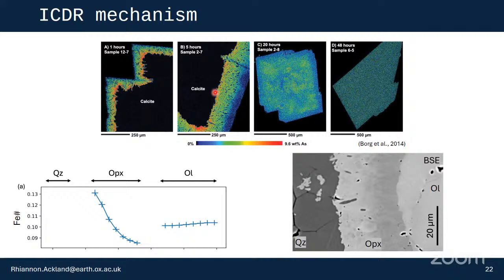nanoporosity of the rims. And as these experiments ran to completion, they did eventually equilibrate and become homogeneous apatite in equilibrium with the fluid. But this trend is very similar to that which I see in my rims with the distribution of iron.